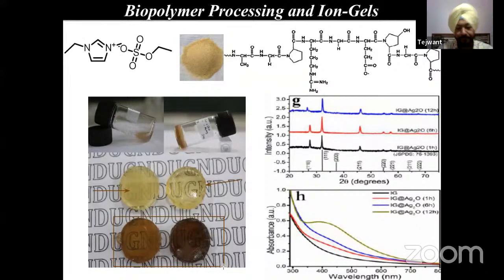Now, because these are gels and the ionic liquid is in continuous motion inside the gel, one can use these gels as solid state electrolytes. So we have explored the ionic conductivity of these gels as a function of frequency and as a function of temperature, and it was found that the gels are very good conductors of electricity and can be used as solid state electrolytes. Besides that, to be used as a solid state electrolyte, there are certain properties which a gel must adhere to.